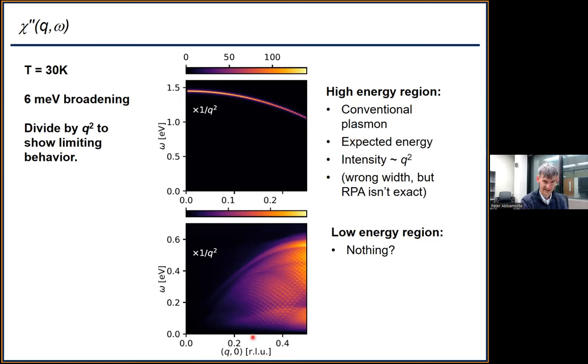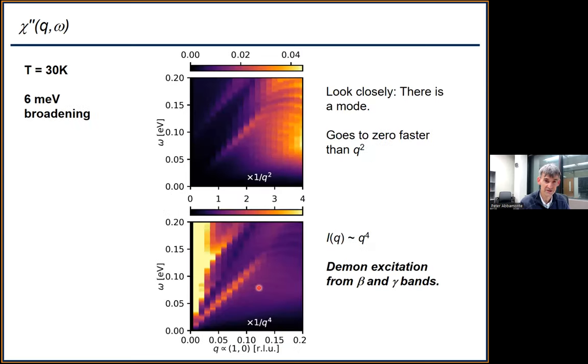So this is the same data, just now on a much lower energy and momentum scale. And if you look in there, what you see is nothing. And we thought, oh, well, I guess there's not a demon. There must be something really wrong. But if you look closely and just zoom in on the intensity, actually there's a mode there. It's hard to see. So if you take chi double prime, multiply by 1/Q², you see a mode, but its intensity is going to zero.